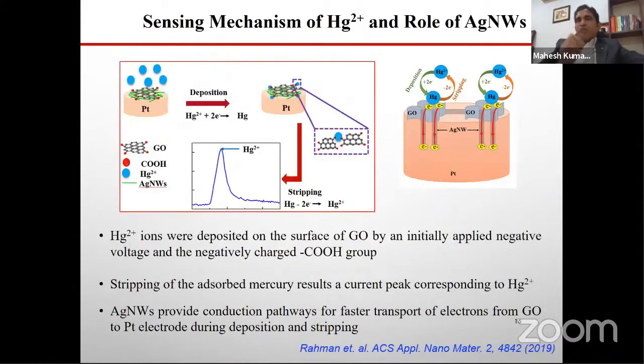So what we have done is modify the working electrode. To modify it, we used graphene oxide, which we synthesized by the standard Hummers method. Because graphene oxide conductivity is less, we mixed it with silver nanowires. Between them is the COOH, carboxylic group. The mercury ion is trapped at a particular voltage, and when these ions are adsorbed, charge transfer takes place at a particular voltage, and for mercury, for example, we get this current.